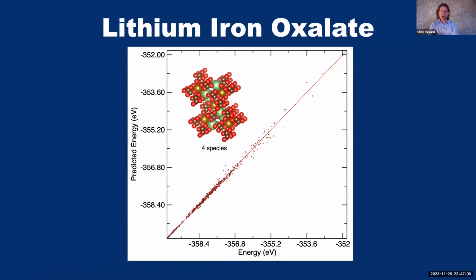And so here is an example for lithium iron oxalate. So that's a quaternary system with 4 different species. And what it emphasizes here is that the way that we put the algorithm together, and by this iterative active learning process, the descriptive power of the potential is focused towards the low energy part of the energy landscape. And so you can see that there's a very low error in the low energy part of this landscape here, but we tolerate higher errors at higher energies.